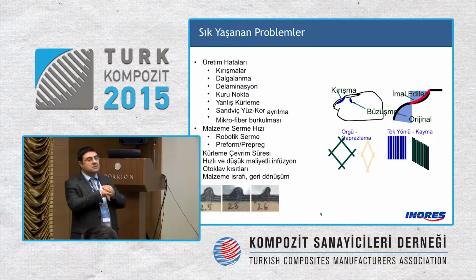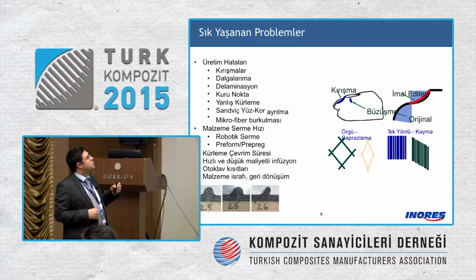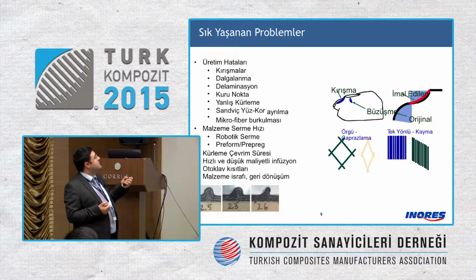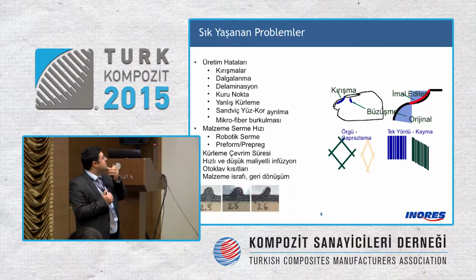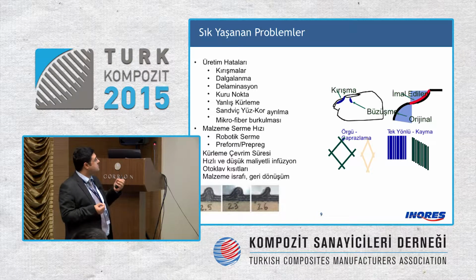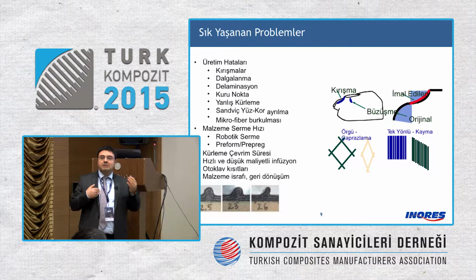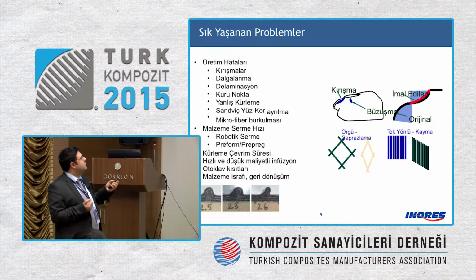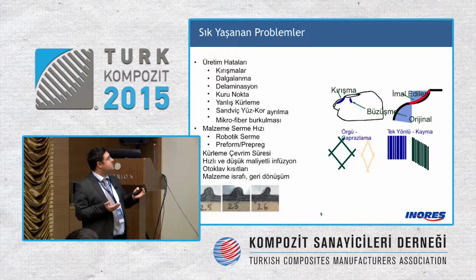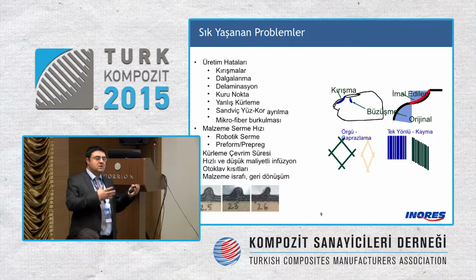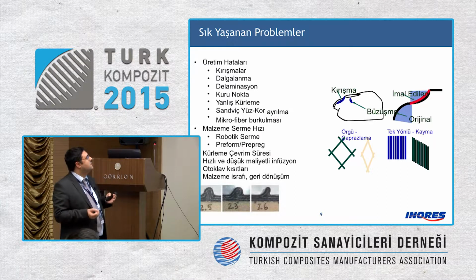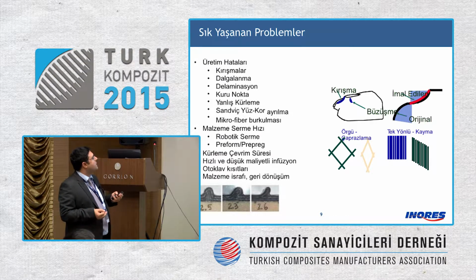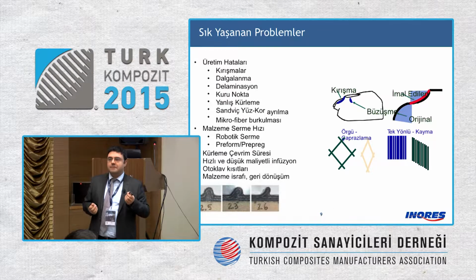The fabric is flexible and it can crease when it's not handled properly. Waving and delamination might occur, and if the fiber is not wetted totally, there might be some dry points. Wrong curing, sandwich face-core separation, and microfiber buckling might happen. Of course, in order to have profitable and high quality production, we need to lay it as fast as possible, and we have to use products which have been prepared before.